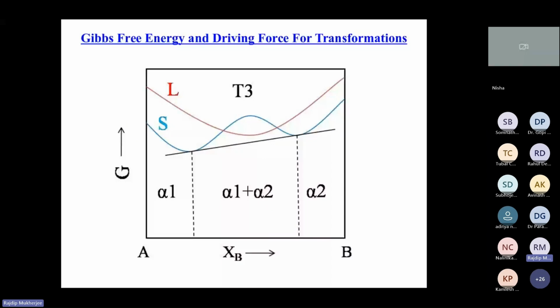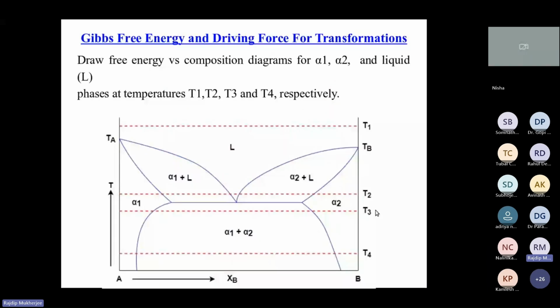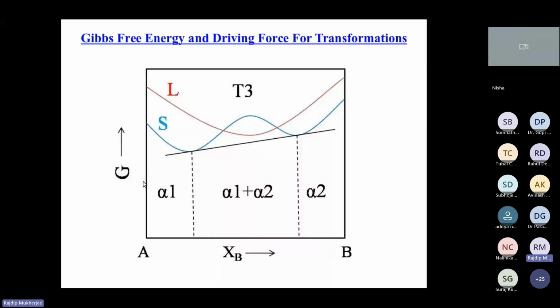So say for T3 temperature, which is below the eutectic temperature, the liquid is solidified into two phases, alpha 1 and alpha 2. So you can see that at T3, the liquid phase free energy will be higher, while the solid phase free energy will be lower. That means at this temperature, the solid phase is more stable, and the liquid will decompose into two solid phases, and their equilibrium compositions will be dictated by these common tangent points, right? So this will be the composition of alpha 1 and alpha 2 when the liquid decomposes into two solid phases.